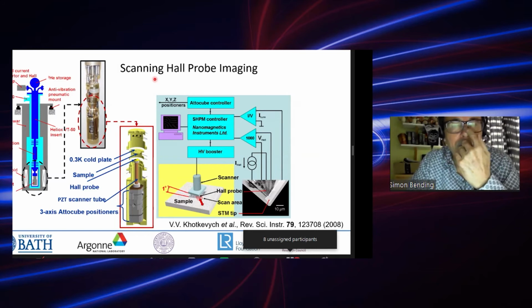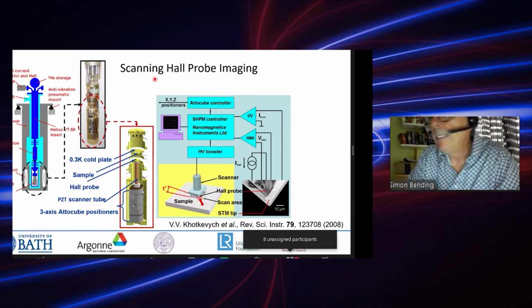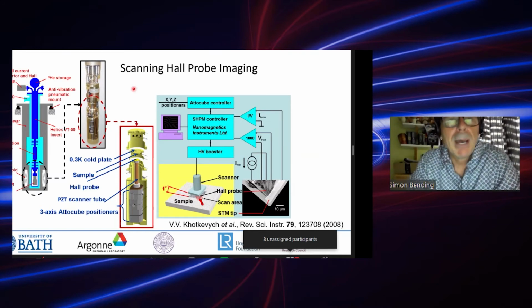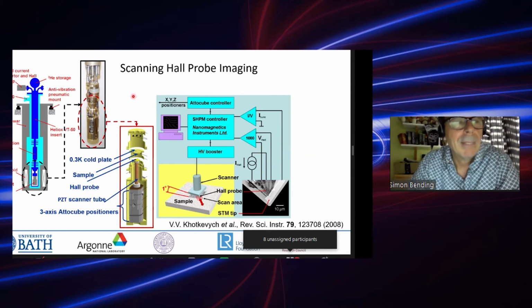So our approach to looking at the problem was to look at the local superconducting properties, and by that we're going to image vortices and try and characterize the local superconducting properties from the vortex profiles themselves. To do that, we use a technique we've been using for many years in Bath, which is scanning Hall probe imaging. This is a diagram of our 3rd generation scanning Hall probe microscope, which essentially is based on an